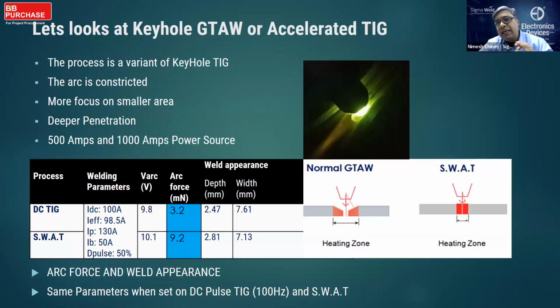We can do something called keyhole TIG welding. When you do keyhole TIG, the arc is constricted, you get a more focused area, deeper penetration. The arc is so focused that you get 3 times the arc force. Therefore, you have larger penetration and lower heat input.